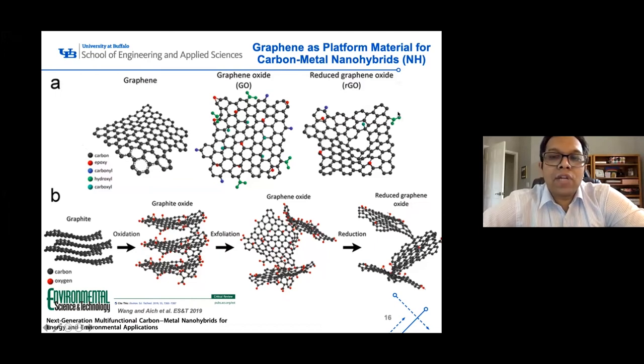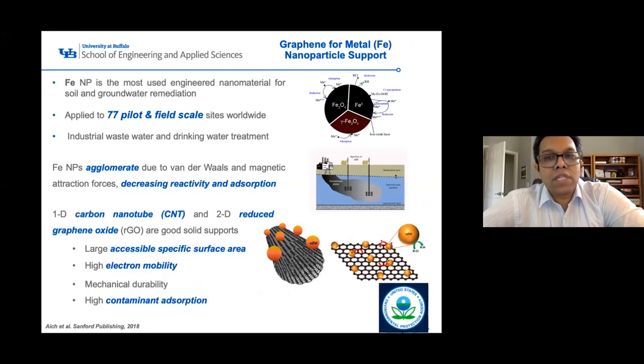To retain this conductivity, you can reduce the graphene oxide, which still has some functional groups to allow for dispersibility and retain the electrical conductivity. So that's what we use typically for supporting different metal oxide nanoparticles. So what we are using as the metal nanoparticle here is iron.